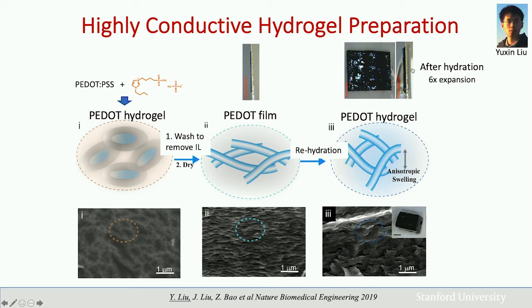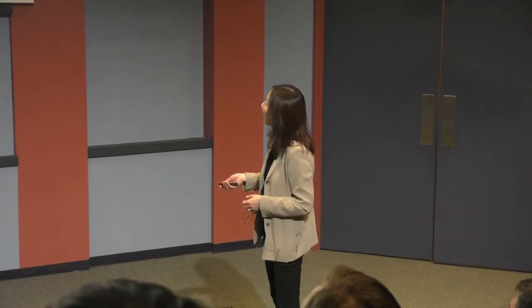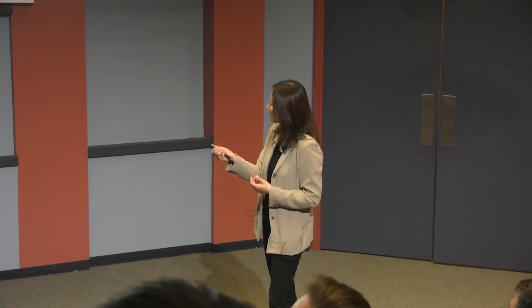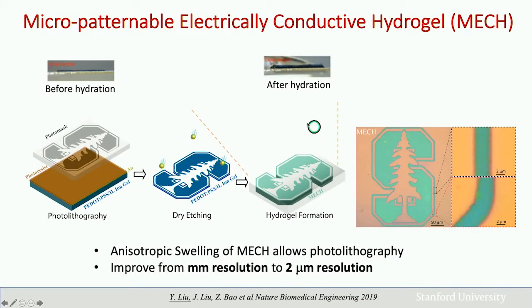But the conduction network is being maintained so that we still have very, very high conductivity, but then the absorbed water makes these materials have a modulus that's on par with our tissue, in the order of kilopascal. So this is the hydrogel that we pattern, and these are patterns that we can produce into these hydrogels with micron resolution.